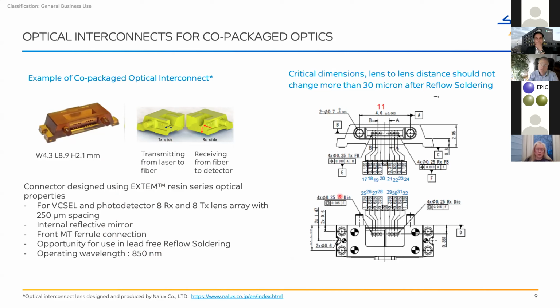So the OEM in America said, well, it is very important to have the lens-to-lens distance, and this is just a schematic diagram of all the different distances in the part. So number 17 to 32 are the lens-to-lens distances from the side as well as from the die side. They should not change their dimension more than 30 micron after reflow soldering, because if it's more than 30 micron, you would lose a lot of optical signal.